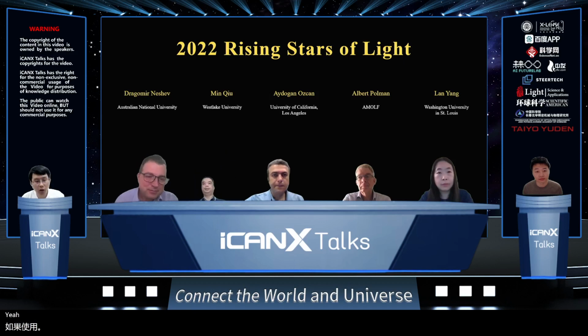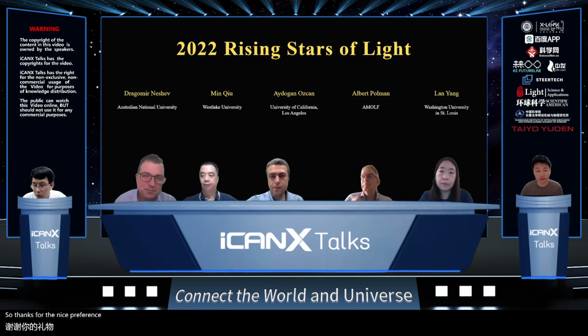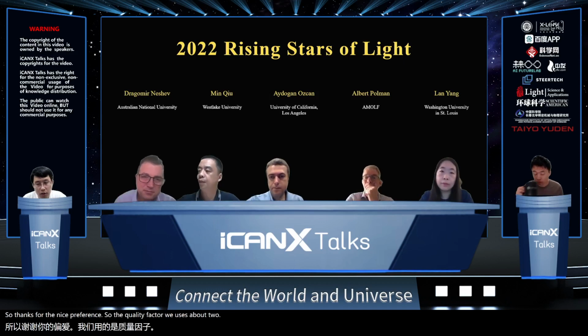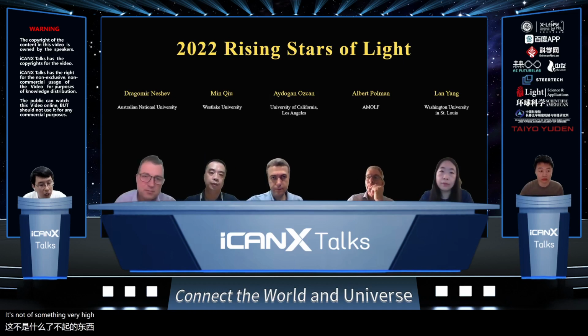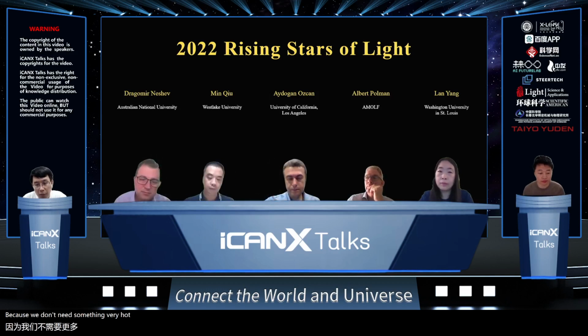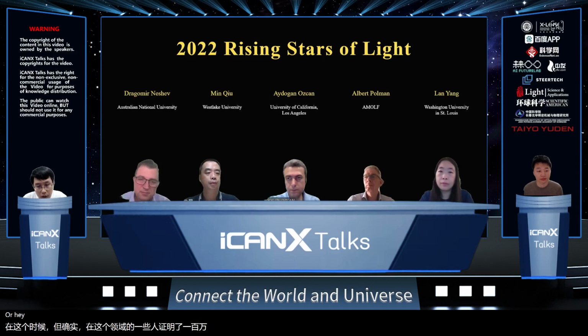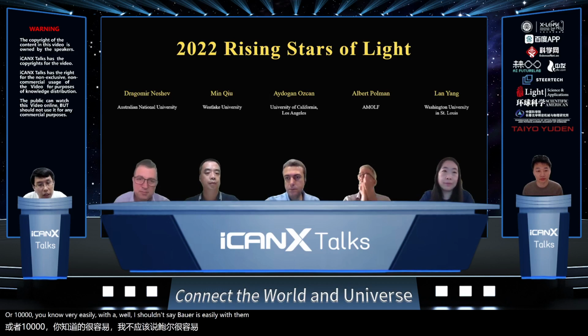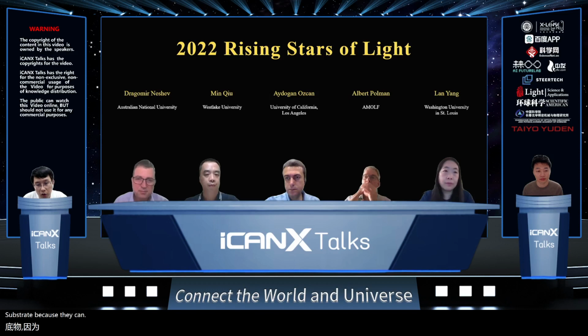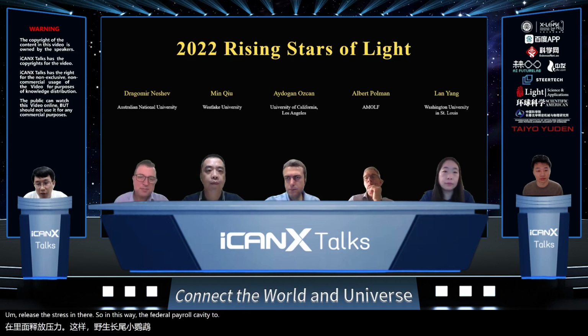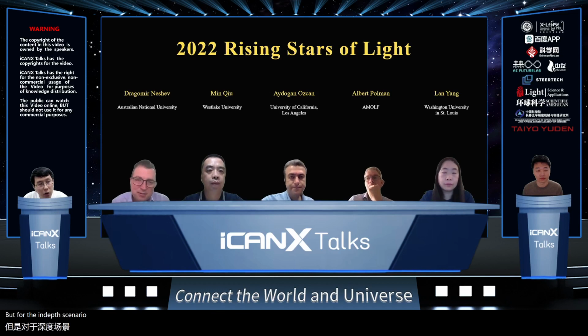Yeah, so thanks to Dragomir for the nice questions. The quality factor we use is about 2000. It's not something very high because we don't need something very high at this moment. But indeed, some people in the field demonstrate 1 million or 10,000, though I shouldn't say very easily, with MBE grown substrates, because they can grow these over multiple days and fully release the stress in there. In this way, the Fabry-Perot cavity Q can be very high. But in that scenario, you will suffer a little bit with low temperature operation. For us, we do room temperature.